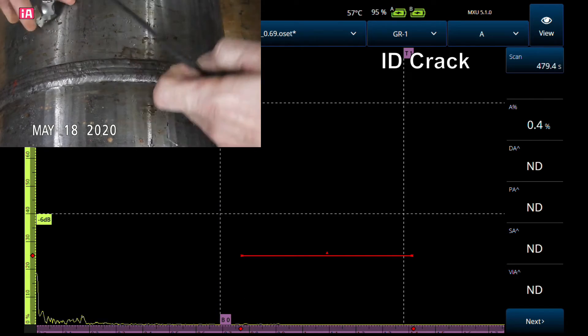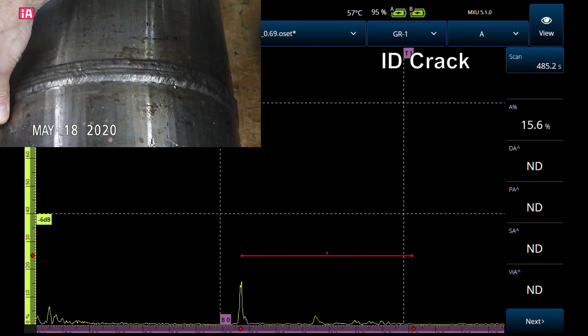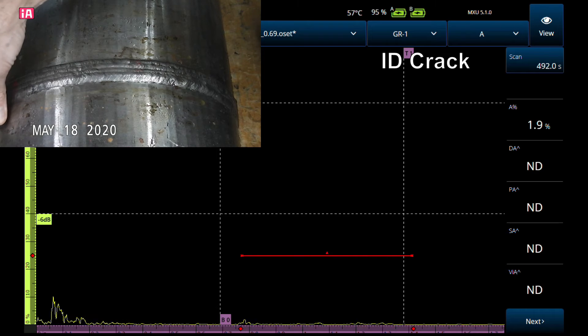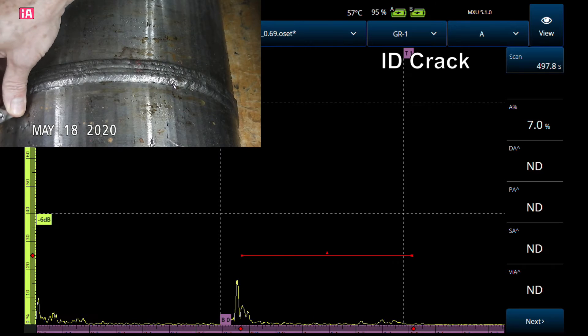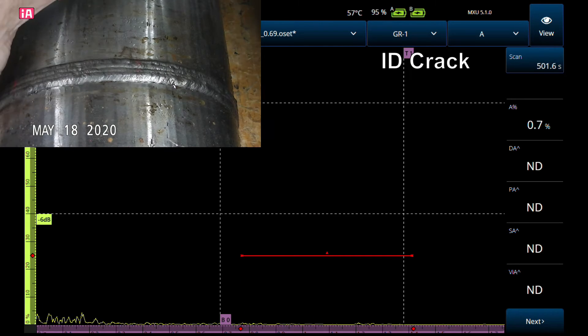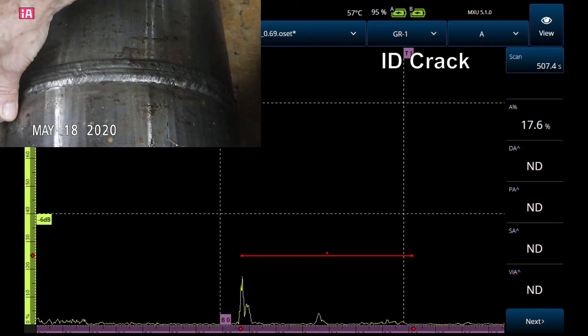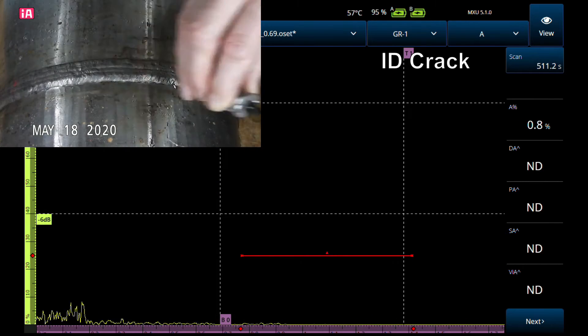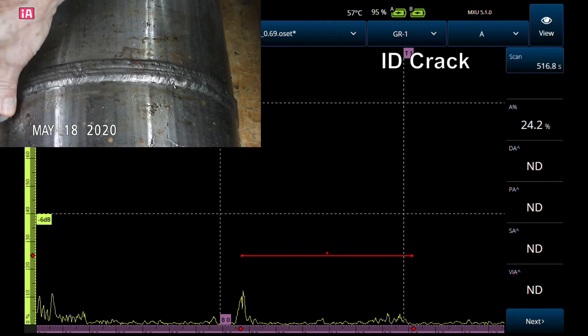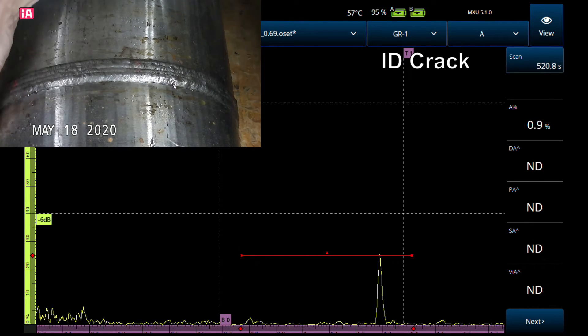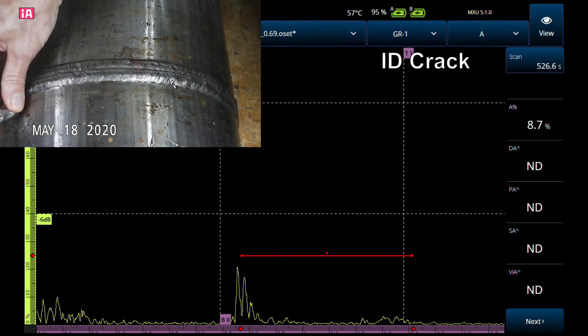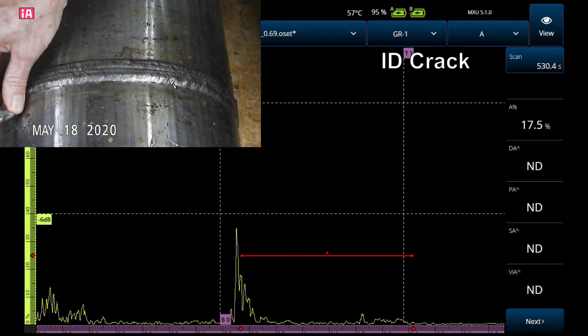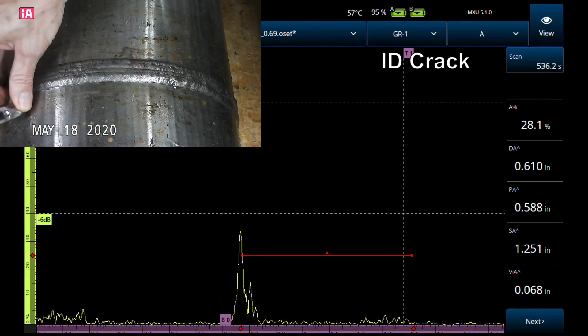Now let's look at the other side. That signal you see there past the white dash line—that white dash line represents the ID surface—so that signal right there is from the root of the weld. You run along the toe of the weld, you can tell that's geometry, and then at some point it should pop up. Let's go plus six again. You can see it right there.